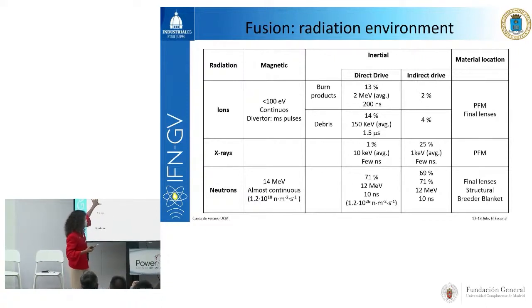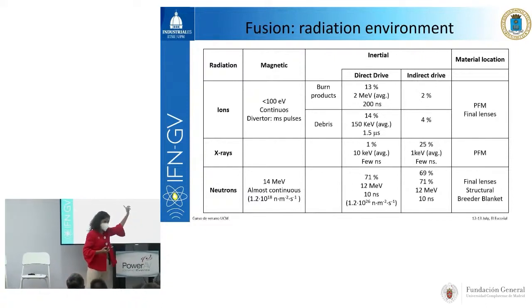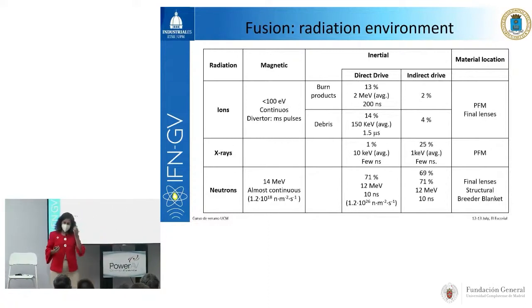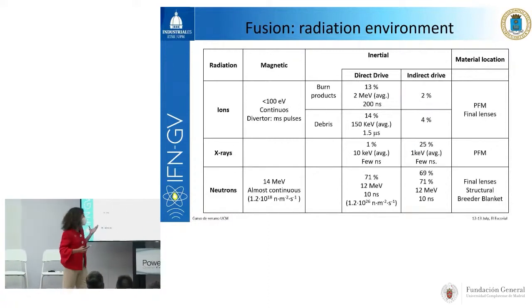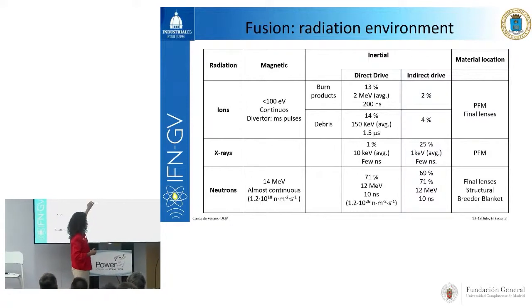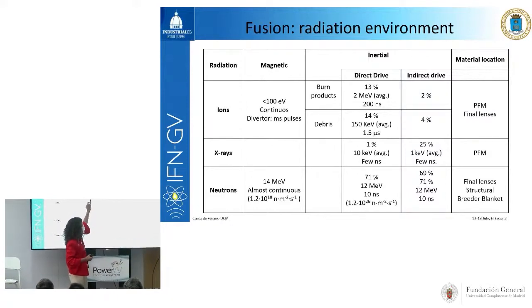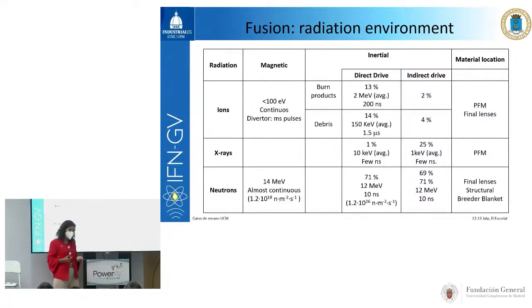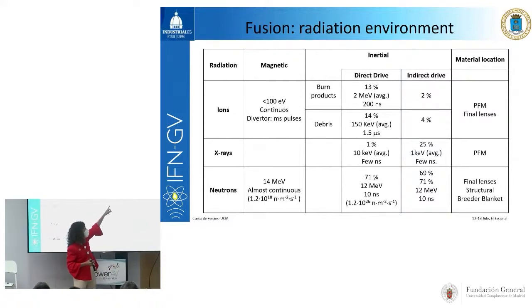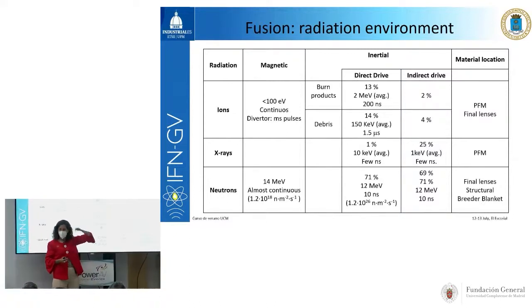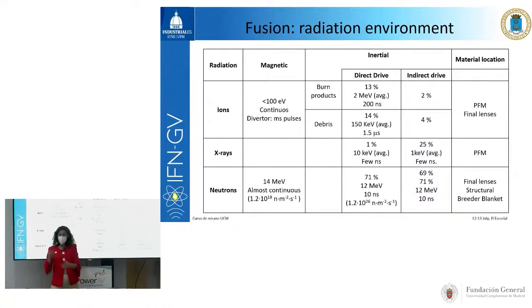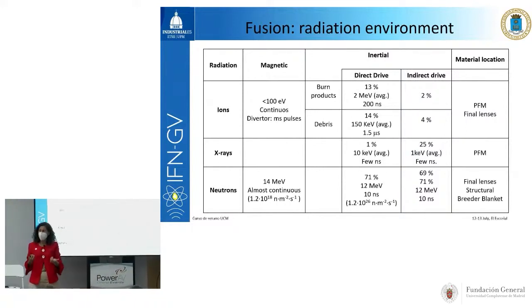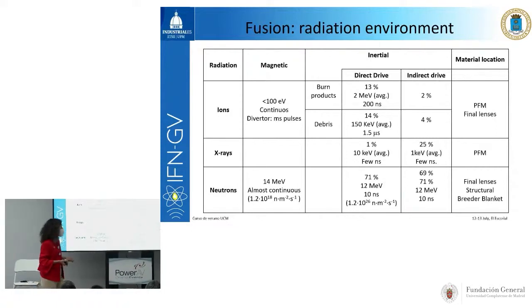If we stay on ions, but we go to the inertial fusion reactor, basically we may distinguish between the ions produced directly by the burn products, and in this particular case, we are going to have very high energetic ions, okay? The average energy is going to be around 2 MeV. And the pulse duration is going to be hundreds of nanoseconds.